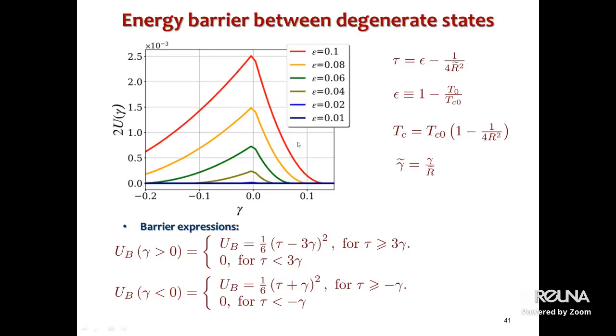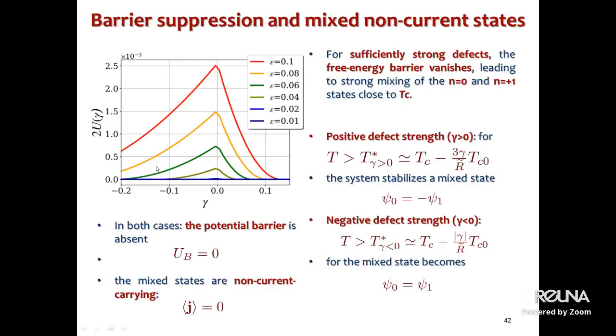Above some critical value, which depends on the reduced temperature, we do not have a barrier. For example, for a certain value of defect, we do not have a barrier. And this temperature, branching temperature, I will call it, depends on the defect strength. For specific defect strength, the barrier vanishes, as I said. And this leads to a strong mixing of the zero harmonic and one harmonic, since we do not have any barrier between them in free energy, so they start to mix.